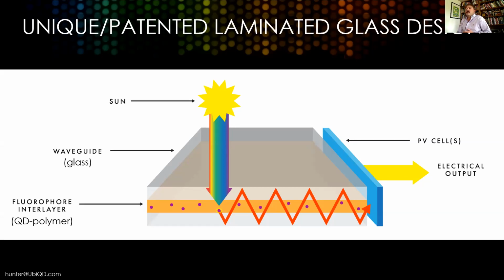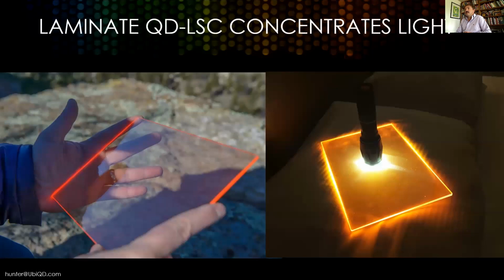And now we're leveraging this to deploy quantum dots, because you can't put quantum dots easily into the glass, but we know how to put them into polymers. And so if we can just put them into that middle layer between 2 sheets of glass, well, you've got a nice monolithic piece of glass that can be integrated into a window relatively easily. And so this does work quite well, actually. So we've done this with various kinds of glass, and you can see that concentration effect. And I'm showing here some visible emitting quantum dots, but generally we use near-infrared quantum dots for our windows. That will give you the best performance.